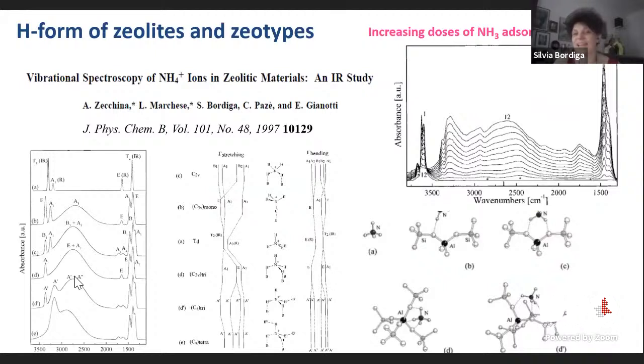Coming to a few examples, I want to recall some studies made in collaboration with Enrica and Leo to characterize the acidity of these materials, zeolites and zeotypes. In this case, the effect of the interaction of ammonia on a SAPO-34 is reported. And here we have studied in detail all the possible interactions of ammonia forming ammonium ion that in the different structures of the zeolite were able to reach a local structure which was different, changing in the symmetry of the ammonium site depending on the local structure of the cavity.